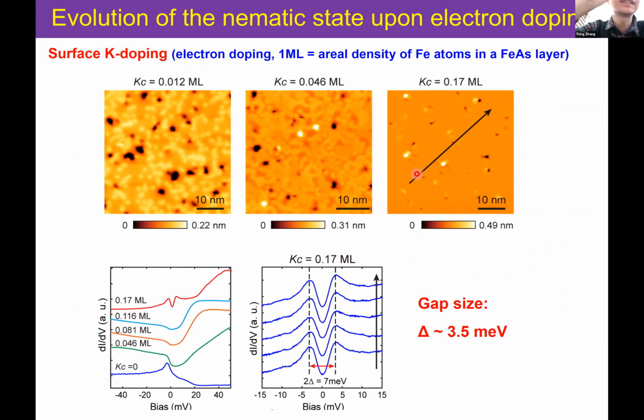And we also checked the surface doping effect. If such unusual nematicity only happens in the heavily hole doped region, then if we dope the surface away from the heavily hole doped region, such as with potassium, which gives electrons on the surface, we can see what happens. So we do this experiment.